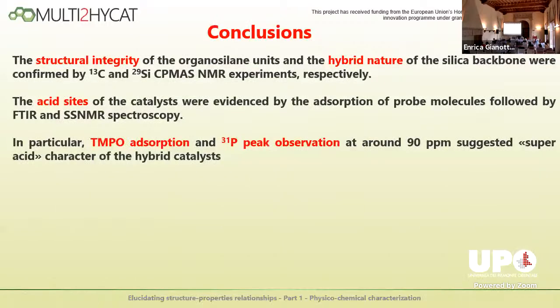So in conclusion, we have demonstrated that by combining, in particular, infrared spectroscopy and solid-state NMR with the use of probe molecules, we can evidence the presence, but also the different strength of acid sites, beside a basic characterization, but very important, of the structural integrity of the organosilane units and the real hybrid nature of the silica backbone by carbon and silicon NMR.